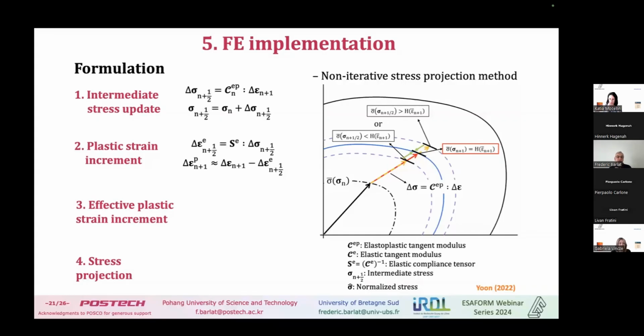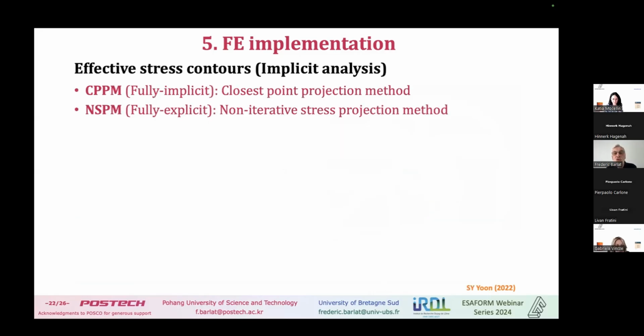And the reason is if we are not at the loading point, and if we have many state variables that are limited, especially not in this model, the variables must be between limits, otherwise the code is going to crash. And so in order to make sure that it is on the yield surface, we have to project the stress we found just before onto the yield surface. And when we do this, we actually get a good integration.